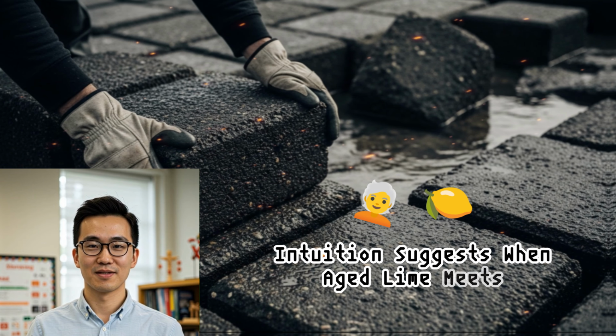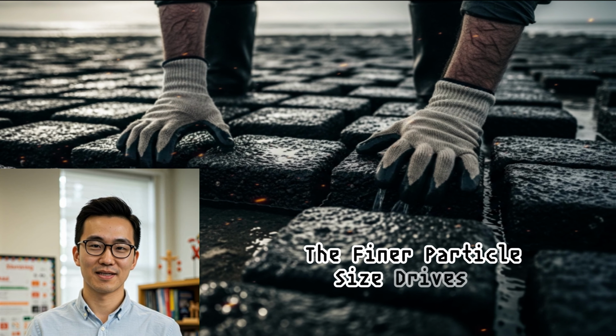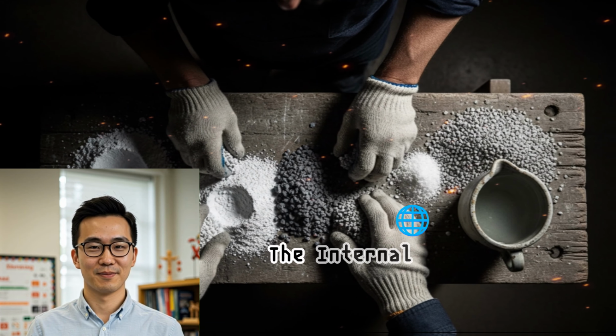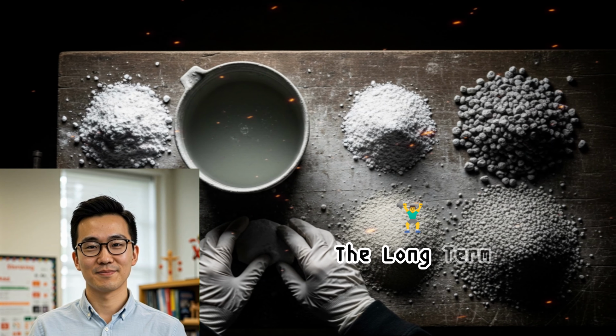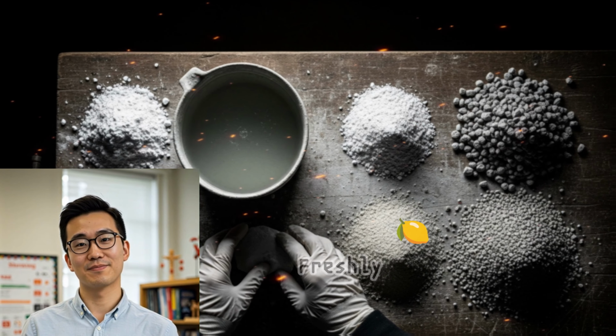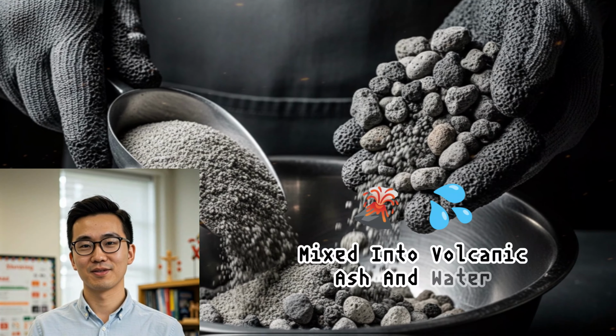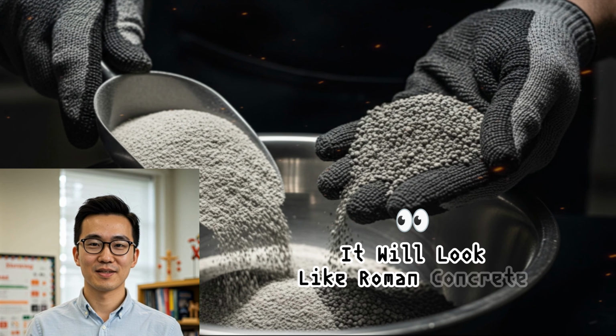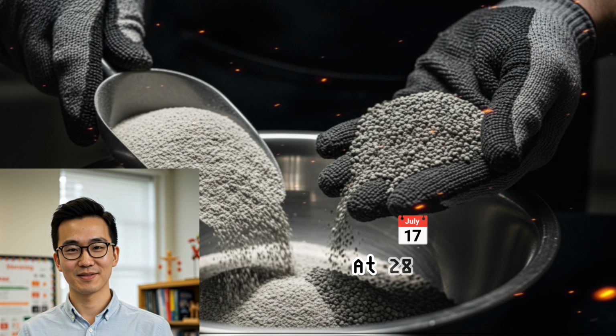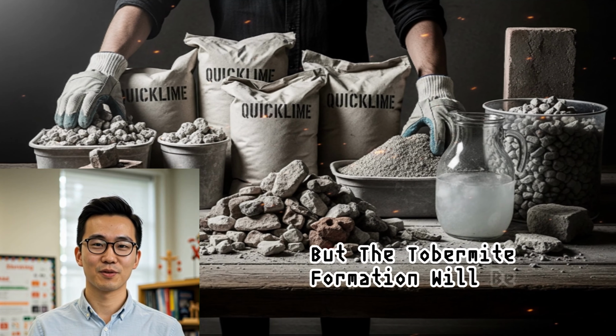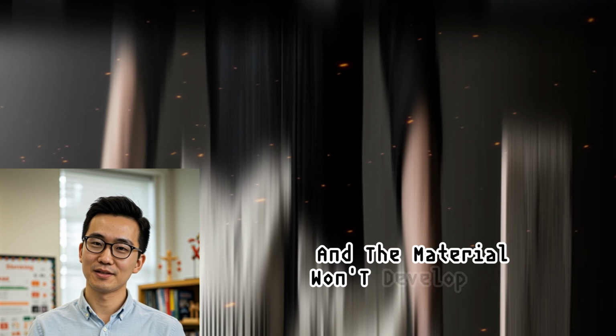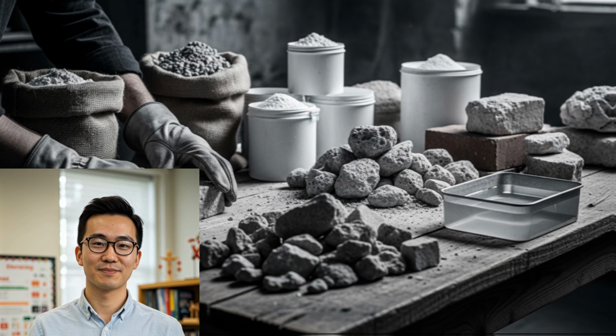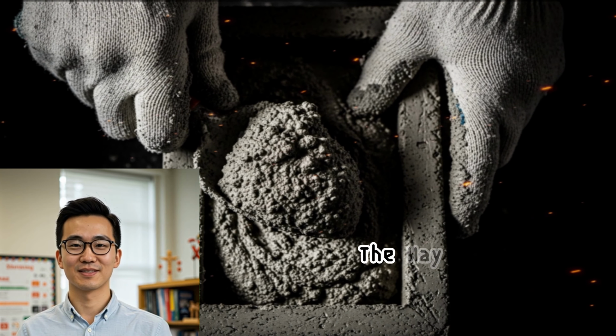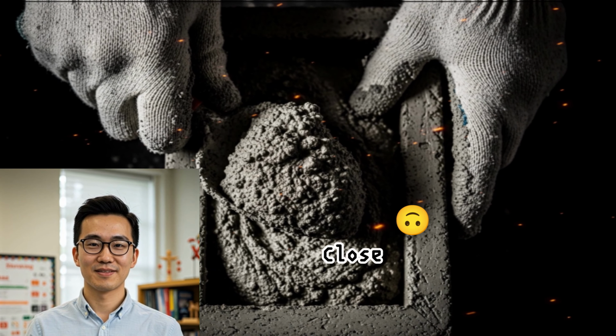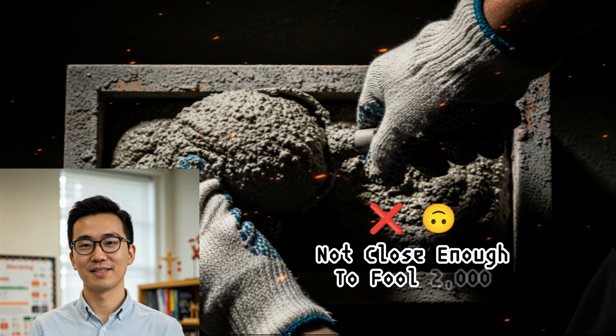When aged lime meets pozzolanic ash, the finer particle size drives a more thorough, more complete pozzolanic reaction. More tobermorite forms. The internal crystalline network is denser. The long-term strength is significantly higher. Freshly slaked lime mixed into volcanic ash and water will still harden. It will look like Roman concrete. It will even test reasonably well at 28 days. But the tobermorite formation will be slower, less complete, and the material won't develop the same long-term crystalline structure. You'll have built something that resembles Roman concrete the way a photocopy resembles an original. Close enough to fool a glance, not close enough to fool 2,000 years.